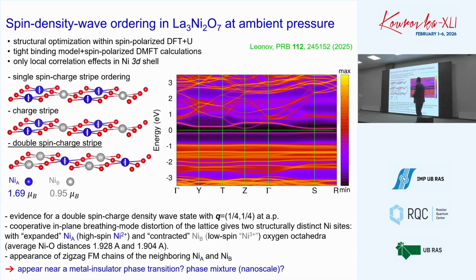We managed to essentially repeat the same calculations which we did for the infinite-layer system, but now for this material. Again, we combine both density functional theory plus U, static mean field to optimize the lattice. Lattice distortions are small, but quite important. We found many different magnetic states, but it turned out that the most stable, in terms of internal energy, was this one. Again, the same story. We have some kind of zigzag ferromagnetic chain of nickel 2 plus, nickel 3 plus.